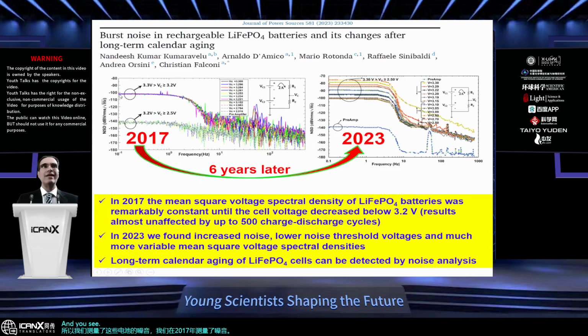So we measured the noise of these batteries in 2017, and you see that we measured almost constant noise down to 3.2 volt. Then, when the voltage of the cell was reduced by the discharge current, we obtained very low noise. In fact, this is dominated by the instrument noise. So we could have high noise, but only for very well charged battery cells.